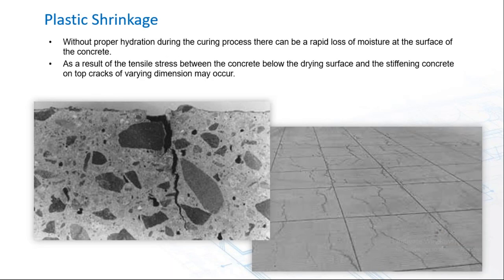Plastic shrinkage typically occurs during the hydration process, where there's a rapid loss of moisture on the surface. And as a result, tensile stresses between the softer concrete below and the harder drying surface above create some internal stress. And then we end up with cracks propagating through the concrete cross section, as you can see there, to varying depths. And once again, now it's a direct route for contaminants and chloride ions, particularly to start their journey towards the reinforcing.